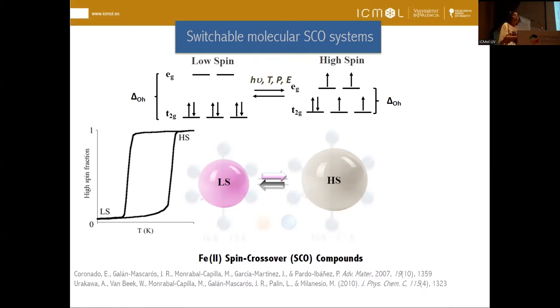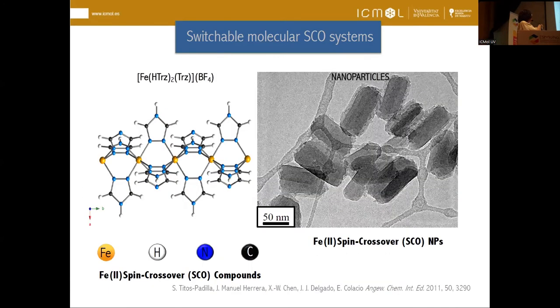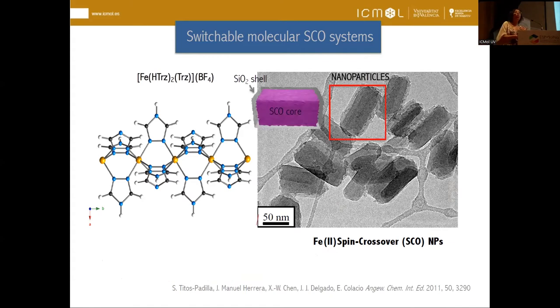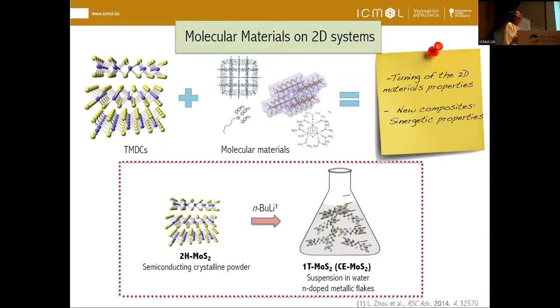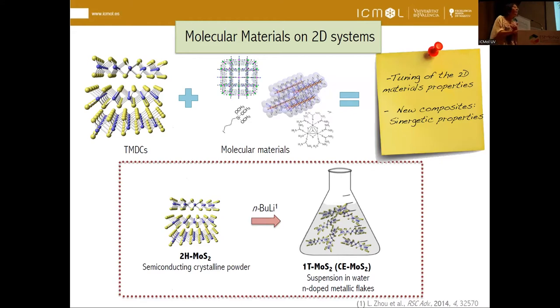So if we attach a spin crossover system on top of our molybdenum disulfide — a system that can change its volume — it could apply a different strain depending on the spin state. We have chosen as our molecular system one of the most common: an iron-triazole coordination compound prepared as nanoparticles with a silicon oxide shell, which helps not only to make it more stable but also for anchoring it to the surface of molybdenum disulfide. It changes spin state with temperature above room temperature. For the molybdenum disulfide preparation, we use chemical exfoliation with butyllithium, which gives an aqueous suspension with the 1T polytype that is highly conductive but the layers are partially reduced — they have a negative charge and are much more reactive.